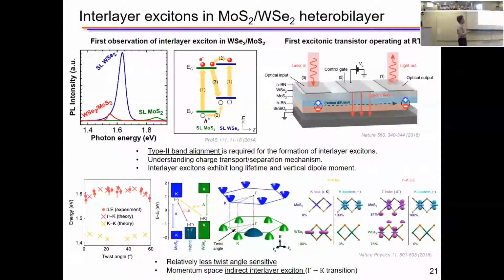I'm interested in this particular combination of molybdenum disulfide and tungsten diselenide. Why is that? Because they are relatively less twist-angle sensitive. When we stack up different 2D materials, there is additional tuning of the twist angle. But if the combination is very sensitive to twist angle, then we cannot claim that the other tuning we're interested in, in this case mechanical strain, plays the major role here. So that's why I chose this platform, less twist-angle sensitive.